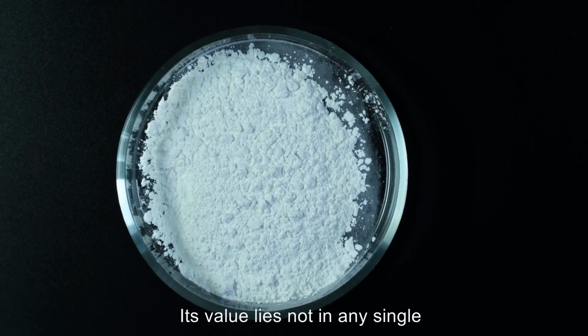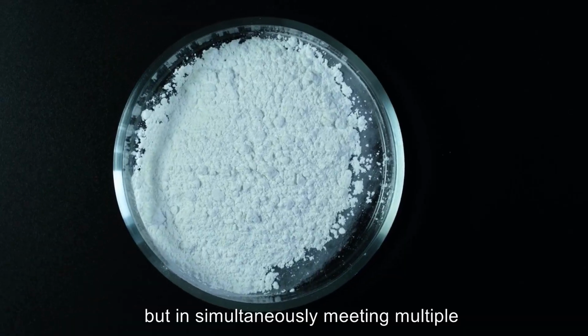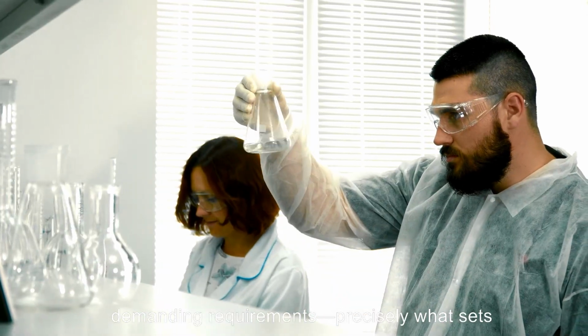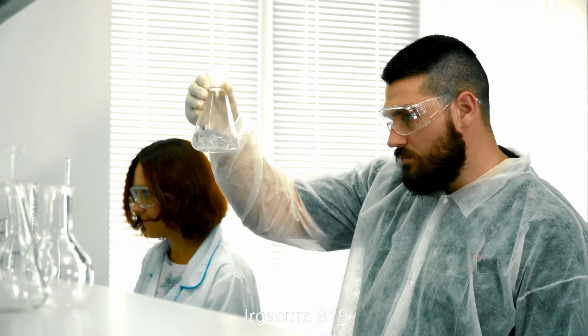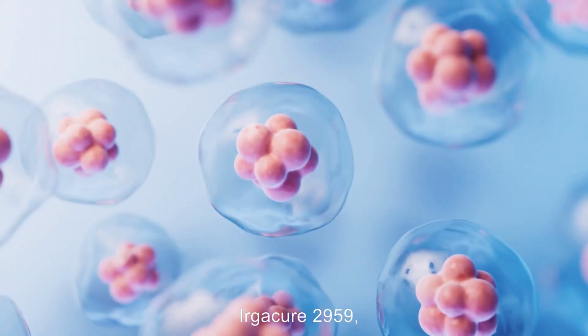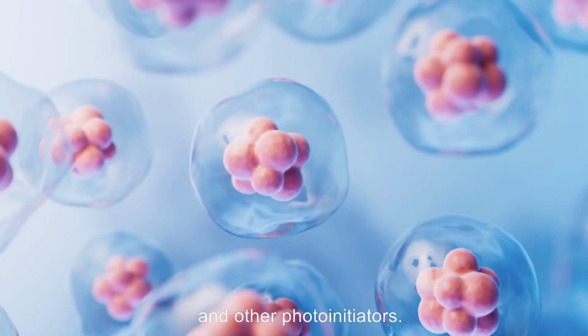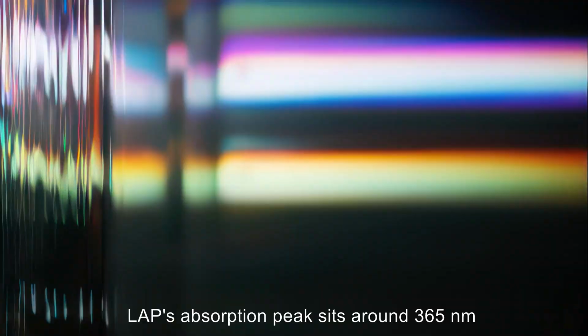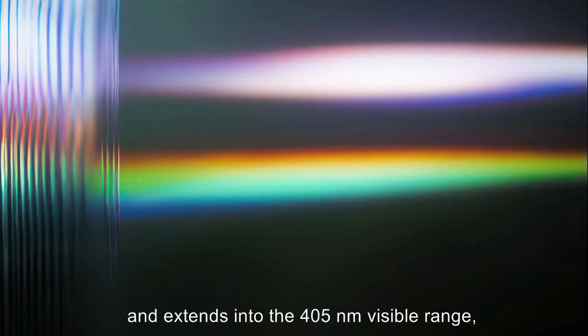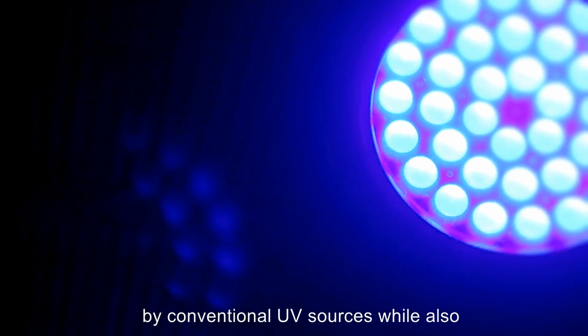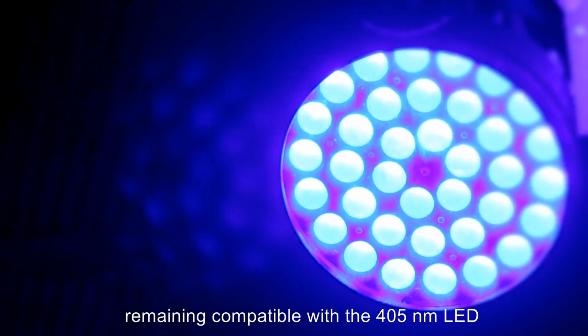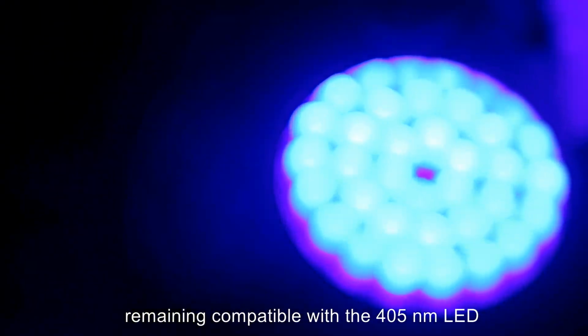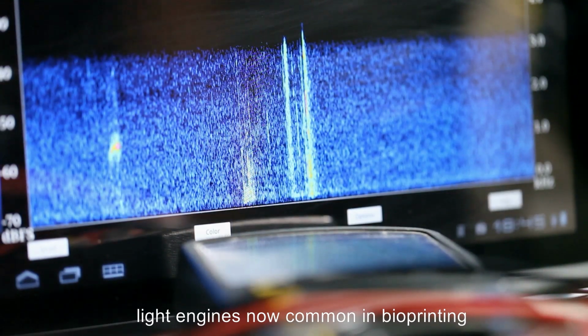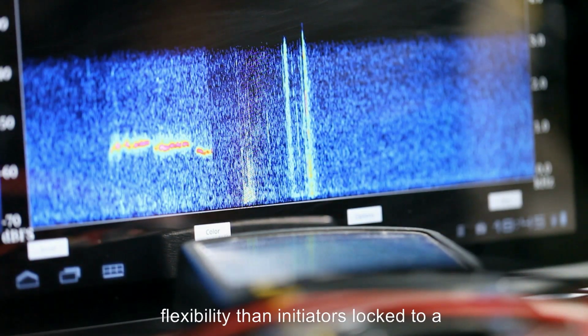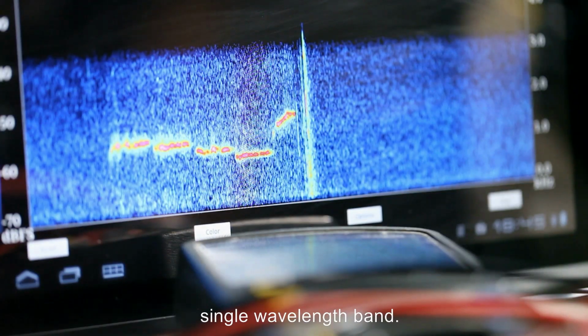Its value lies not in any single best-in-class parameter, but in simultaneously meeting multiple demanding requirements, precisely what sets it apart from TPO, Irgacure 819, Irgacure 2959, Eosin-Y, and other photoinitiators. LAP's absorption peak sits around 365 nanometers and extends into the 405 nanometer visible range, allowing it to be efficiently activated by conventional UV sources, while also remaining compatible with the 405 nanometer LED light engines, now common in bioprinting equipment, giving it far greater flexibility than initiators locked to a single wavelength band.